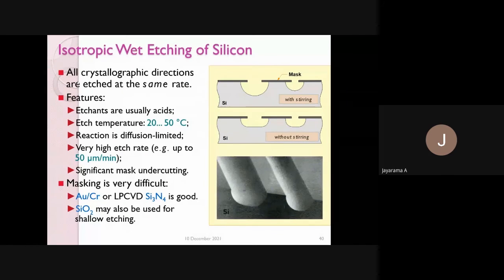The reaction is diffusion limited, and the etch rate is very high, up to 50 micrometer per minute in isotropic wet etching of silicon, and there will be significant mask undercutting. You might have observed undercutting. This is undercutting. Masking is very difficult.